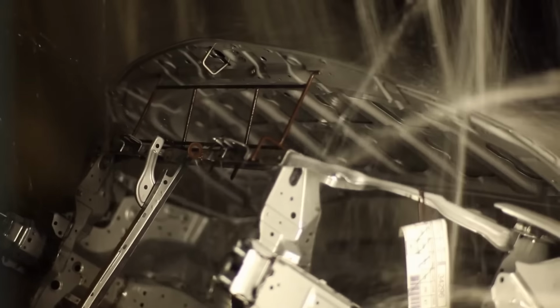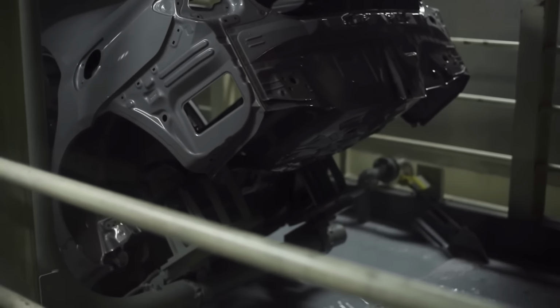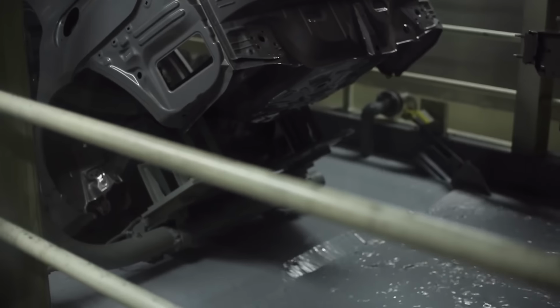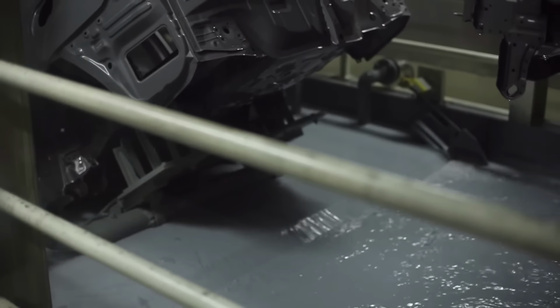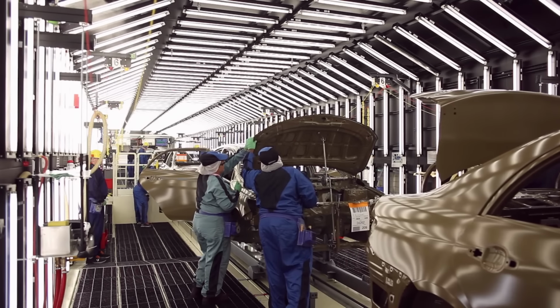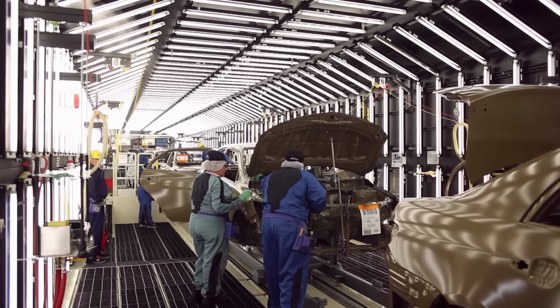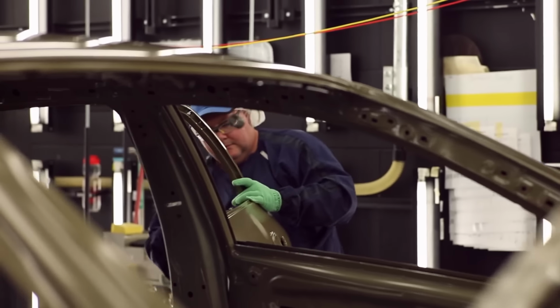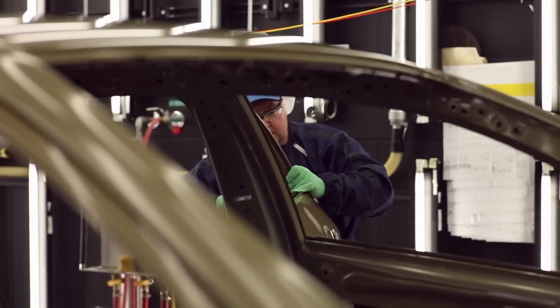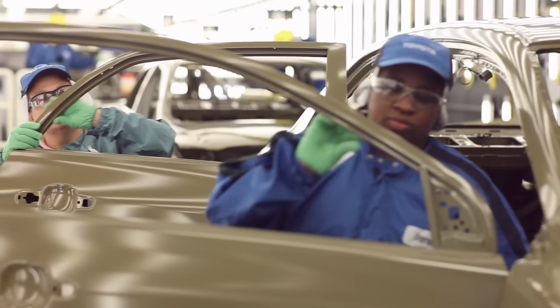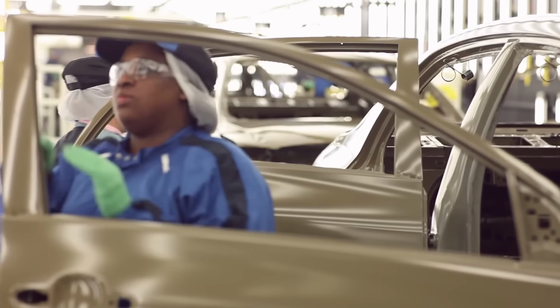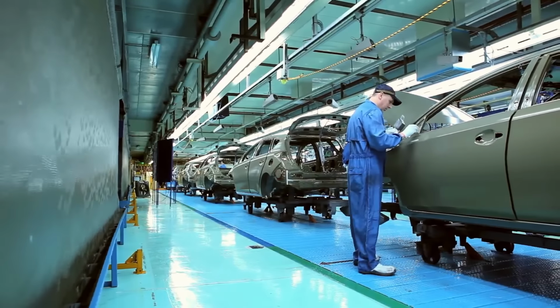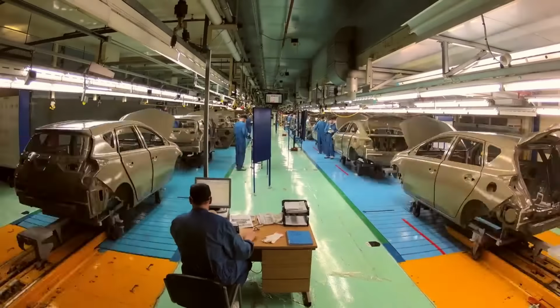In the phosphate treatment, a thin, dense, and uniform phosphate conversion layer is deposited to provide protection against corrosion. In the next step, the automobile body is lowered into an electrodeposition tank containing around 80 to 90% deionized water and a mixture of resin, binder, and a paste consisting of pigments. An electric current is applied to the vehicle body, and the deionized water acts as a carrier for the paint solids, depositing it on the vehicle's surfaces. As the coating grows in thickness, it becomes more and more insulating, slowing down the process. After coating, the vehicle body is then baked at 160 degrees Celsius or 320 degrees Fahrenheit for around 10 minutes, leaving a 15 to 25 micron film that serves as the vehicle's primary defense against corrosion.